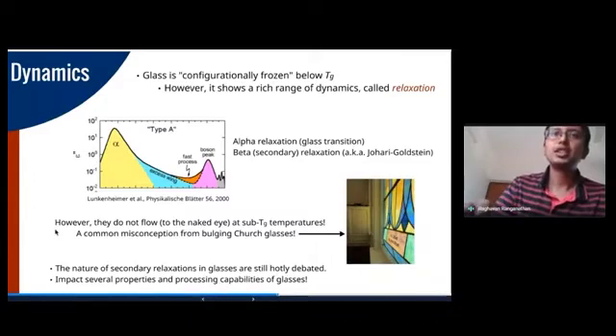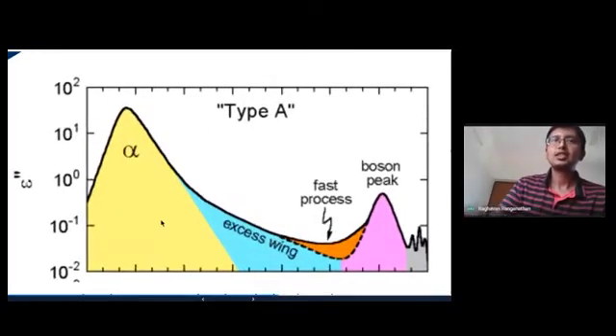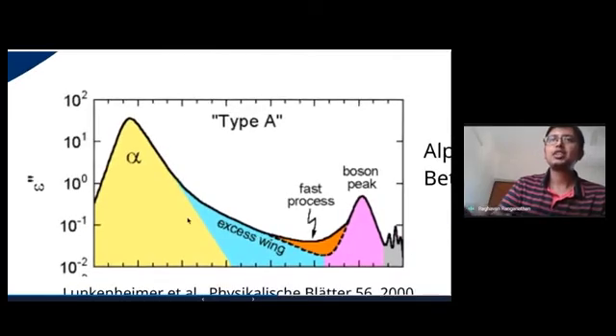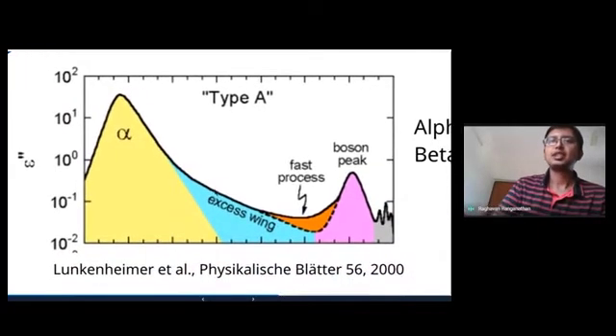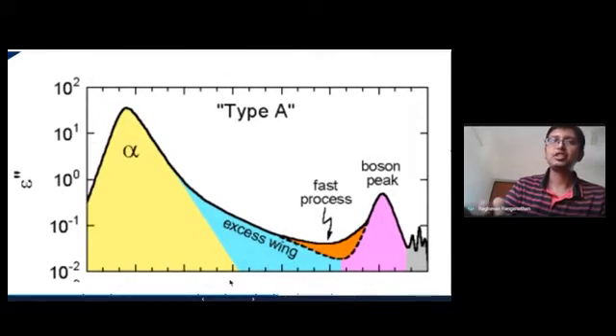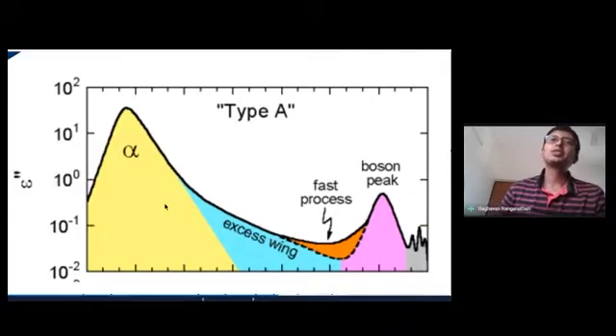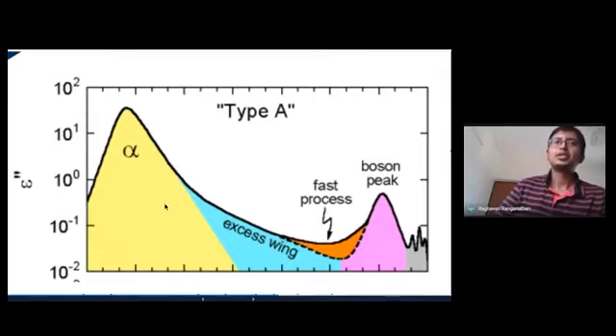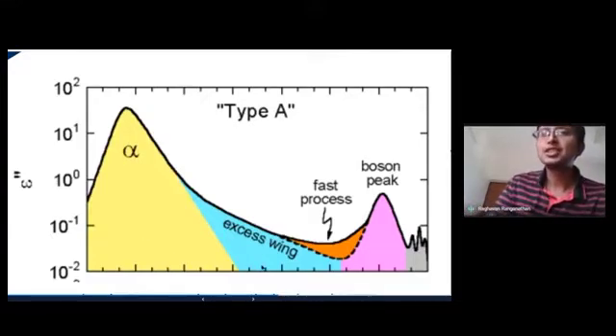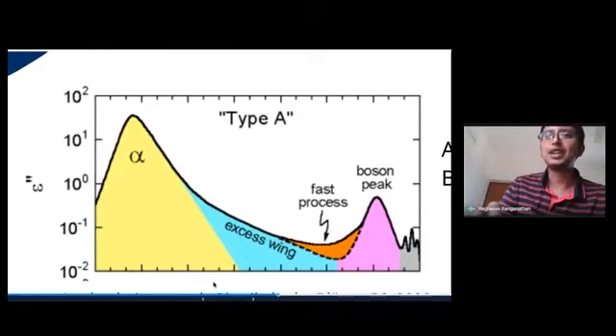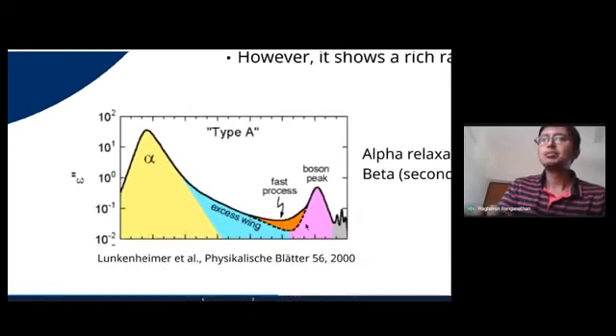What I show here on this graph is some of these atomic displacements, what we call relaxations, as a function of the frequency at which they undergo these deformations. The alpha peak that we see is the traditional glass transition that takes of the order of a few tenths of seconds maybe. I'm sorry, this figure is cut. I'm not able to see the x-axis values here. But essentially what we're trying to probe is the dynamics in glasses as a function of the time scale at which these dynamics happen. I think a better picture would be